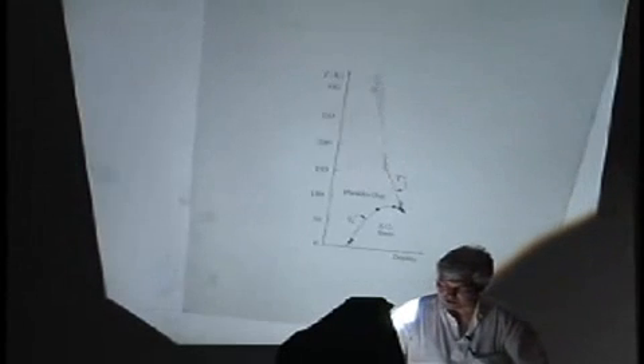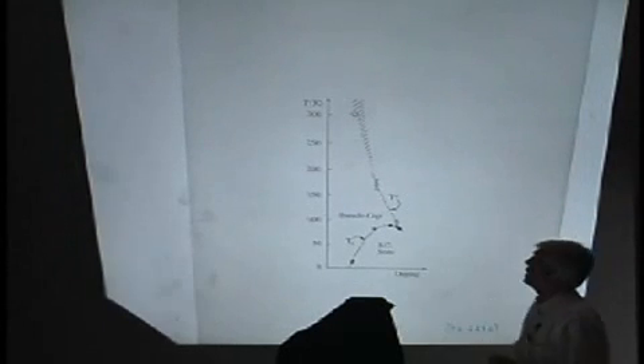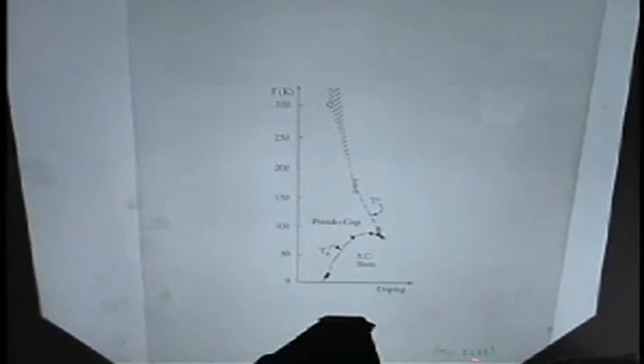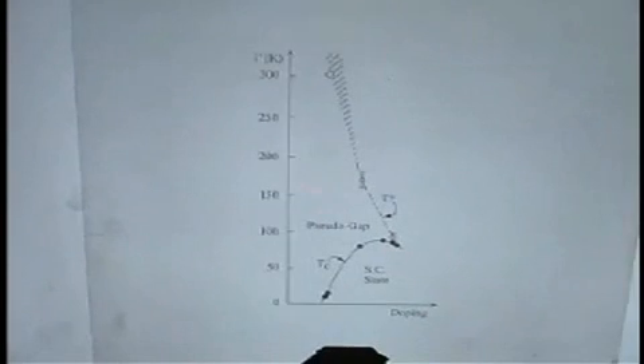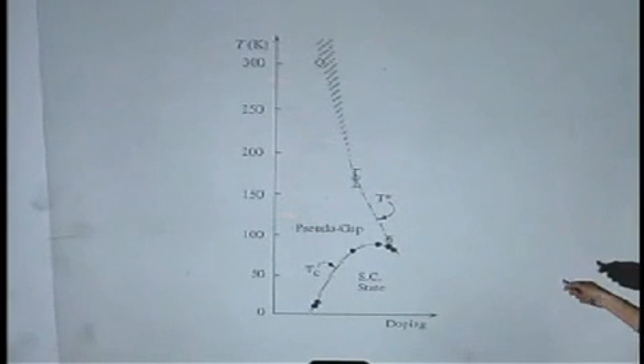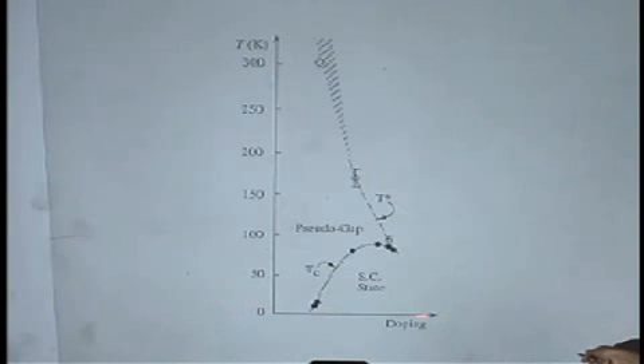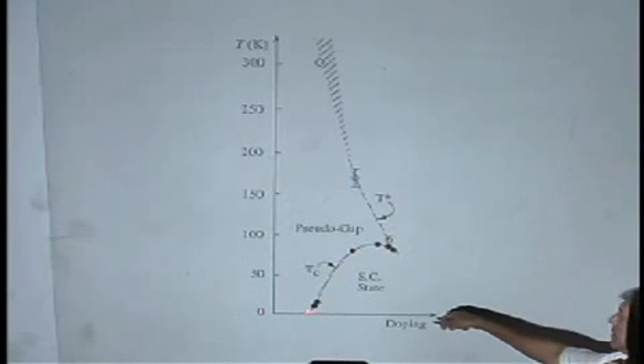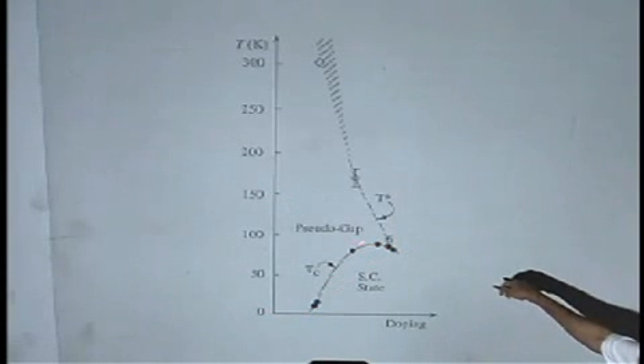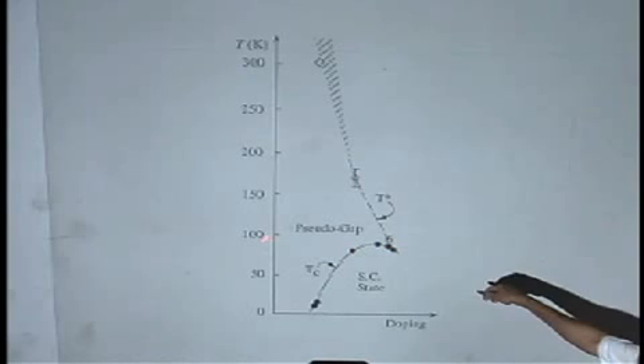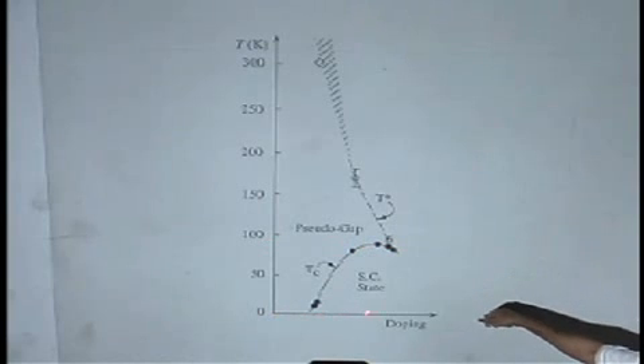Well, this is just a shortcut version of the phase diagram of this high-temperature superconductor, essentially for this bismuth-based compound. It's only part of the phase diagram. This is temperature versus doping. The stoichiometric composition of the system is an antiferromagnetic compound, and the antiferromagnetic phase is not shown here because of its no relevance to what we are going to say. This is the superconducting critical temperature. The system is at optimal doping where the temperature is the highest, is in the underdoped region here and the overdoped region here.